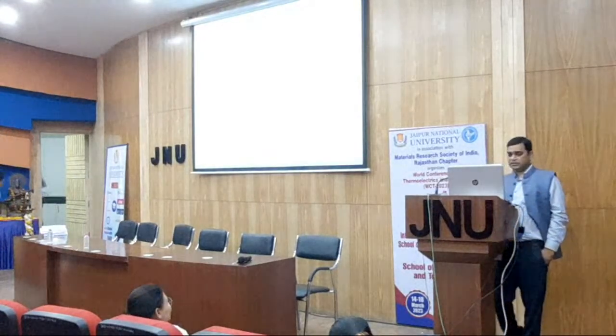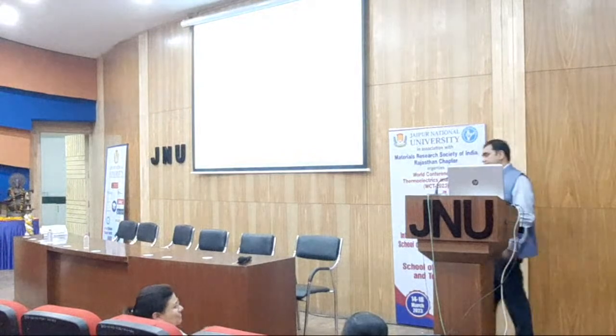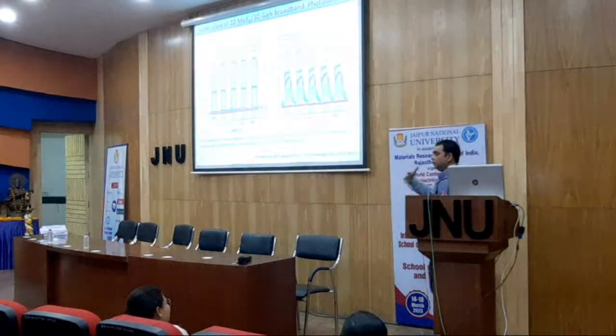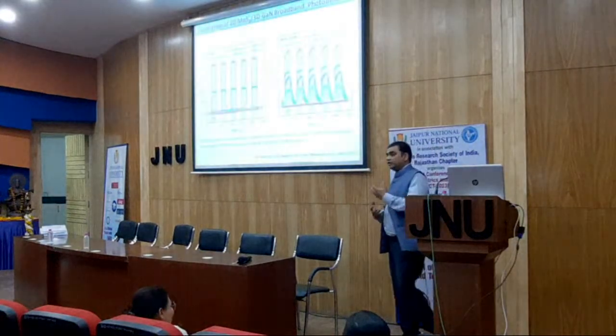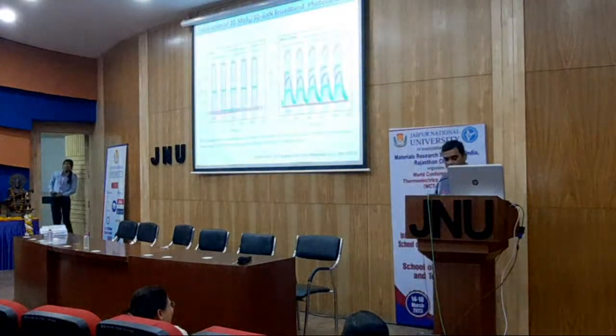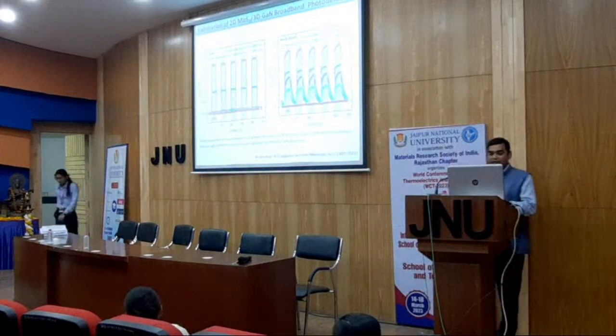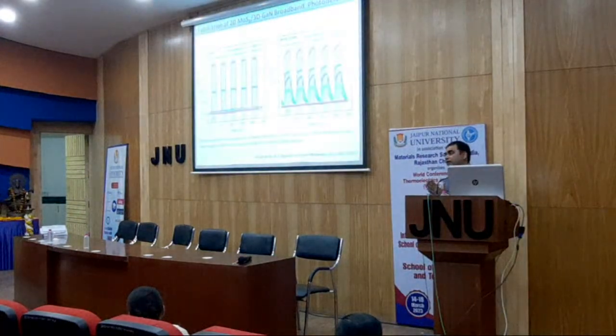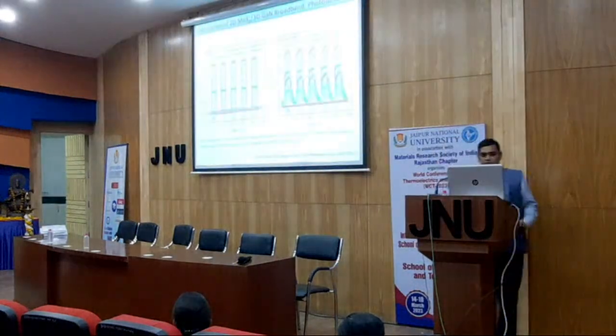Besides this, if you look carefully, the photocurrent is also enhanced by 6 times in the UV range. So that shows not only is the device showing broadband, it is also increasing the charge carriers, because the dislocation, which was the major hurdle for the transport, is being passivated with the presence of MoS2 in this. So I have to go quickly. I have only 1 minute left. I have 40 more slides.